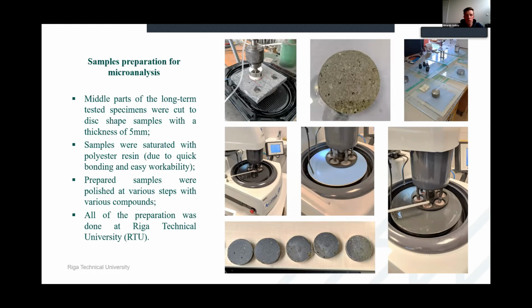Quite an easy procedure. The necessary sections of the creep and shrinkage specimens were saturated with polyester resin to prevent any influence on the element microstructure during the cutting and drilling processes to extract the samples out of the creep specimens and shrinkage specimens. When the cutting and drilling was done, the surface of the cut samples was evaluated, and if the sample didn't have a surface thoroughly saturated with the polyester resin, it was done once again, to prevent unwanted cracks from developing in the polishing part that otherwise wasn't there in the pre-testing part.